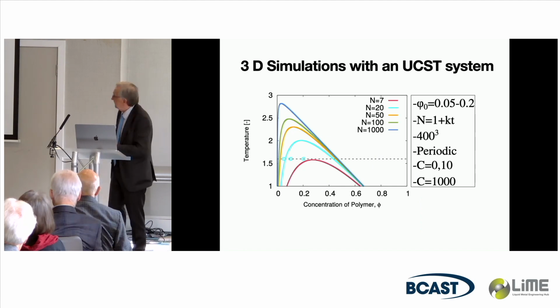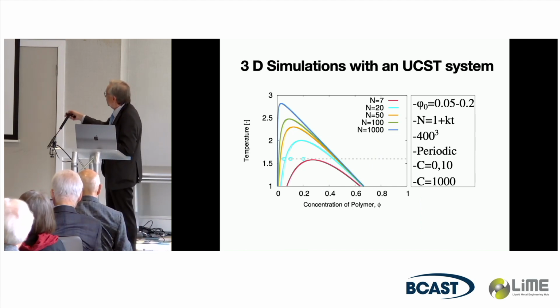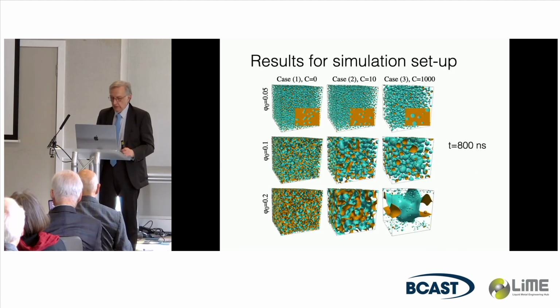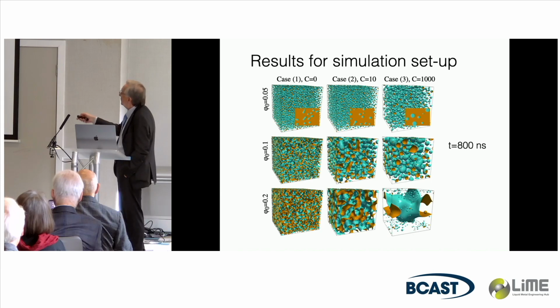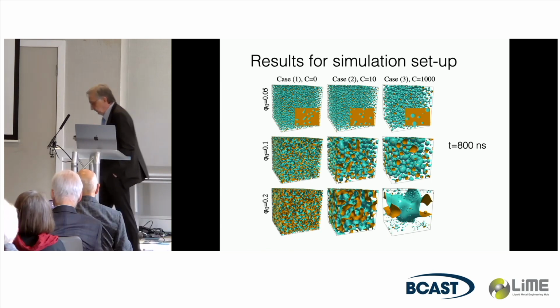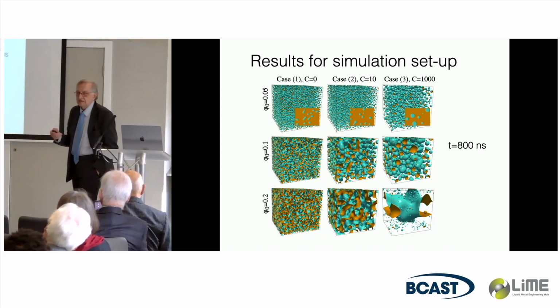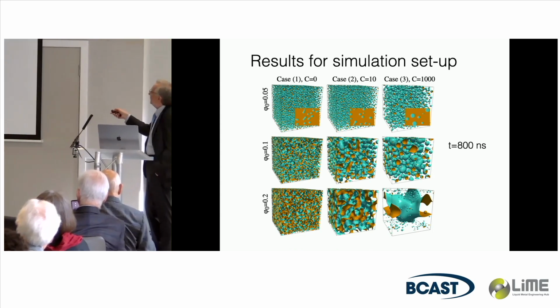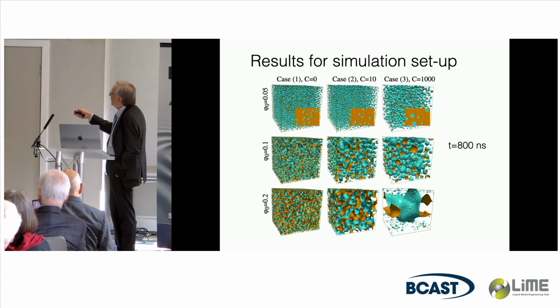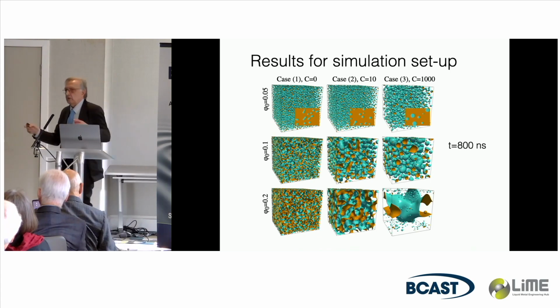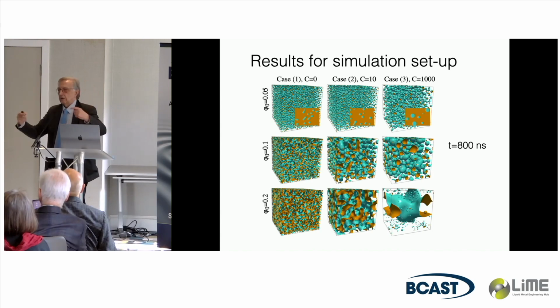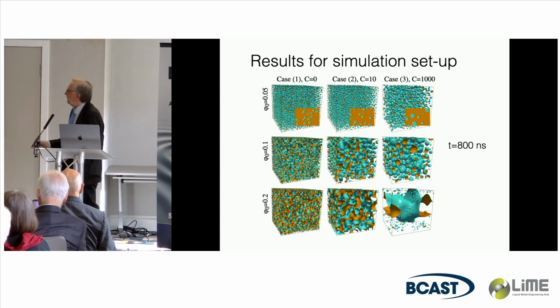So we now go to this system with exactly different volume contents, this point, this point, this point, as a function of time. So we have the degree of polymerization varying and different capillary numbers. And what you see here is what I mentioned. You see exactly a low volume fraction which would mimic monotectic, slightly hypermonotectic alloys. You see at the end with larger capillary numbers, this looks exactly like our 3D tomography of a rapidly quenched immiscible alloy. There's not a big difference.